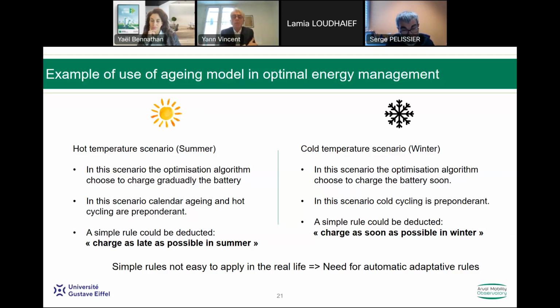And in this case, you will have the maximum effect of the calendar aging. So the best way is to charge as late as possible. It means waiting until the middle of the night, at 1 or 2 o'clock in the morning, to start the charging, in order to have the full charge in the morning at 6, 7 or 8 hours.